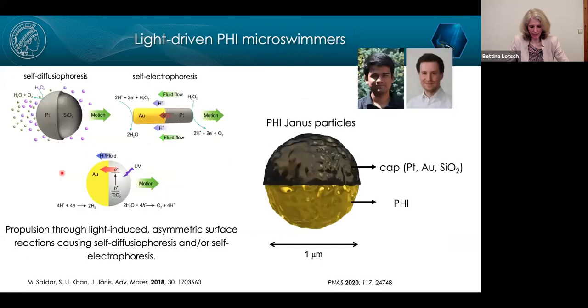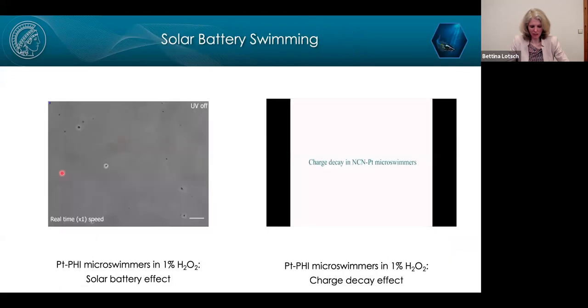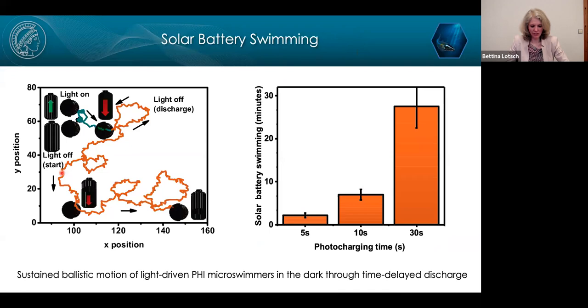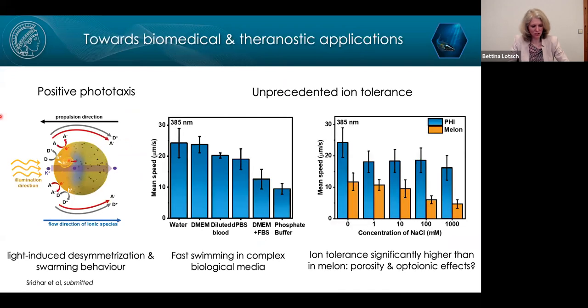Yeah, there is. Actually, I skipped over that far too quickly because I was running out of time. There's a very simple one, which is shown here. These particles swim towards the light. So that is one mechanism of directing them, which is known as positive phototaxis. There could be positive and negative phototaxis. Some particles show phototaxis, some don't, and that typically is a convolution of zeta potential of these particles and swimming mechanism, and little is understood there.